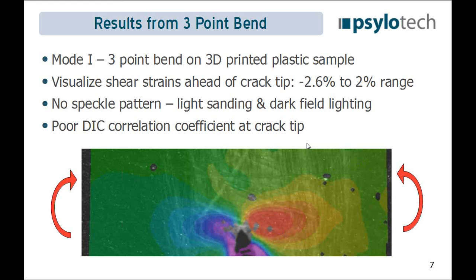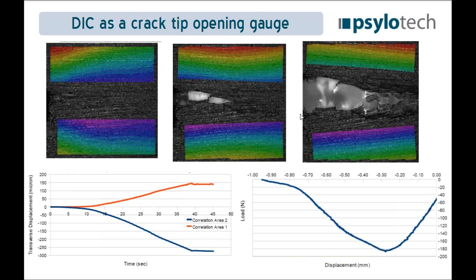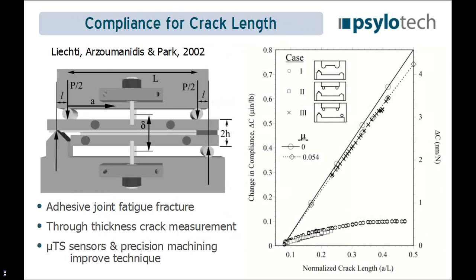Of course, another way of taking advantage of digital image correlation with these under-microscope tests is to just use the displacements that you get from DIC as a crack tip opening gauge. This is actually the same sample, the same 3-point bend mode 1 sample, where we put a block above and below, and we saw how much that block moved on average as the crack was growing, and that gave us a crack tip opening displacement. So, just a pretty standard technique, but with a little bit of a twist, adding DIC instead of having to clamp on a crack tip opening gauge.